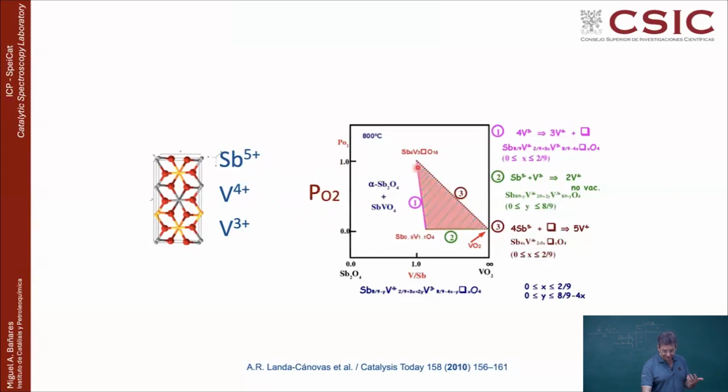And when you did that, antimony atoms were getting out of the lattice. It's a very dynamic system, and just by removing oxygen, I shouldn't say reducing, but not oxidizing anymore, it's like moderate reducing conditions, because you make vacuum and you minimize the partial pressure of oxygen, that really tends to reduce. And then all of a sudden, the system responds by losing antimony on the side.